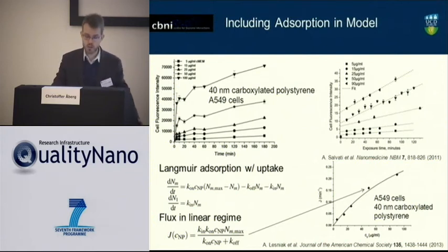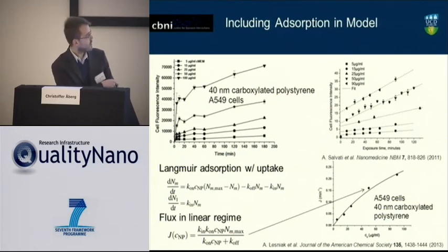So to model this, we have developed a very simple model where we describe the uptake of nanoparticles as first the particle finding a cell and sticking to it, and once it's adsorbed to it, you have to wait a bit longer until it's actually taken up. And you can see that if you write up this kind of equation system here, and you look at the nanoparticle flux, which we have measured experimentally, you again get a rather good fit with experimental data.